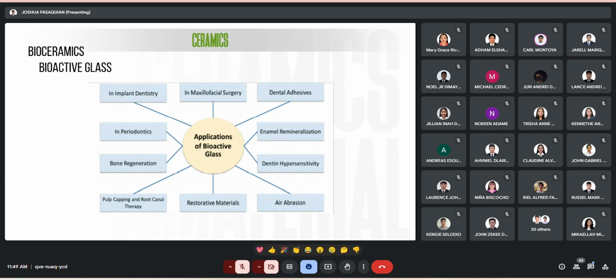That's why other materials are added to the bioactive glass compound. For example, fluoride impregnated bioactive glass was found not only to increase remineralization, but also reduce enzymatic degradation of the dentine collagen network. Also, the increased concentration of silver in bioactive glass resin composite increased the number of dead bacteria in biofilm when compared to other samples. So, we can say that silver enhances the antimicrobial properties of bioactive glass.